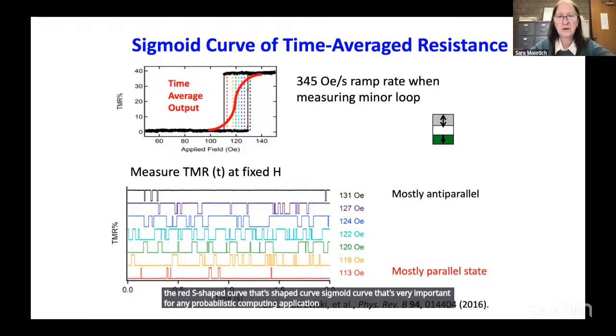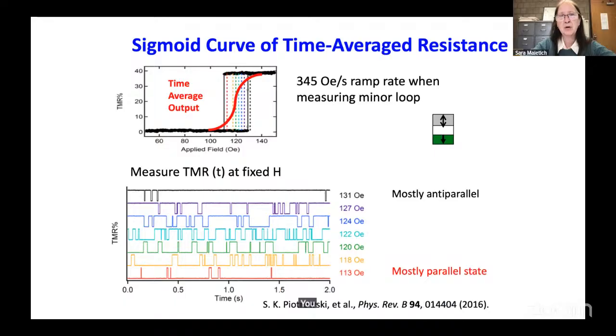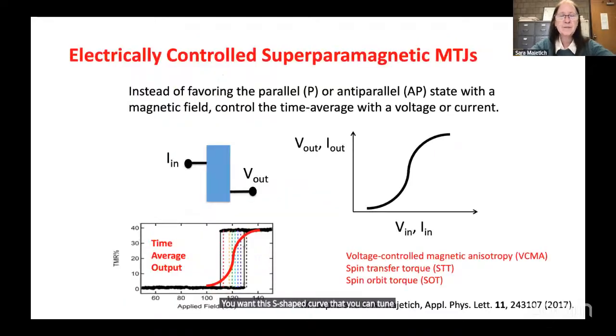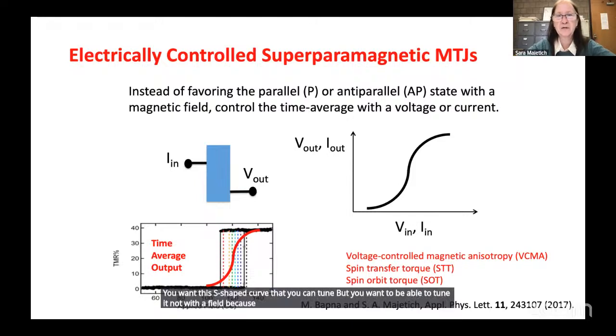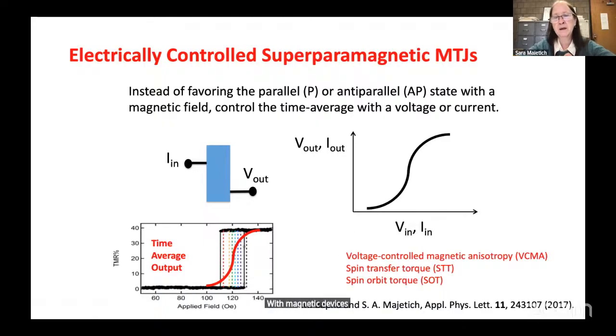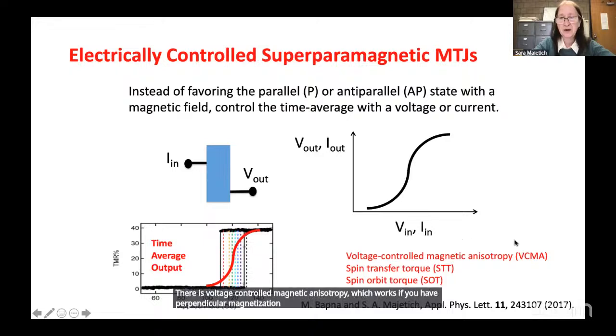So people in quantum computing have different metrics. For probabilistic computing, you want this S-shaped curve that you can tune. But you want to be able to tune it not with a field, because it would be hard to apply a different field to all of your different devices, but fairly straightforward with today's electronics to apply an independent current or voltage. With magnetic devices, in particular the magnetic tunnel junctions, there are three good ways to do this. There is voltage-controlled magnetic anisotropy, which works if you have perpendicular magnetization. It's very, very low energy.